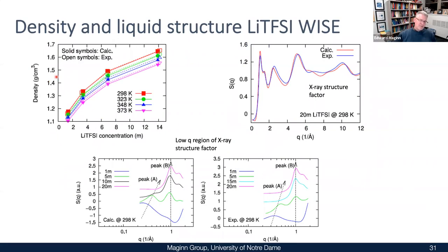So this is the overall density of the system versus LiTFSI concentration at different temperatures. The open symbols are our calculation, or sorry, the experiments, and the solid symbols are our simulations. And we're quantitative, we're within 1% of the densities for all of these.